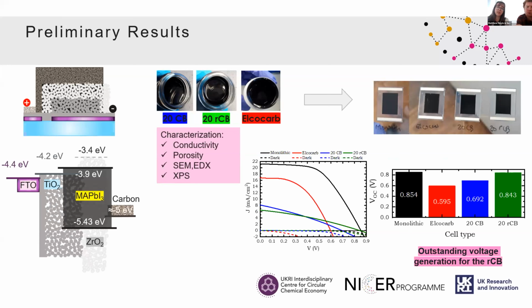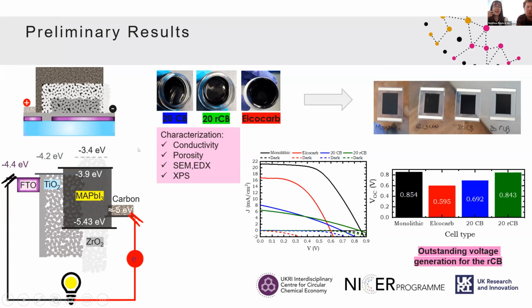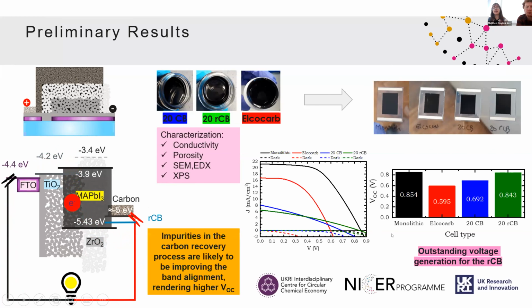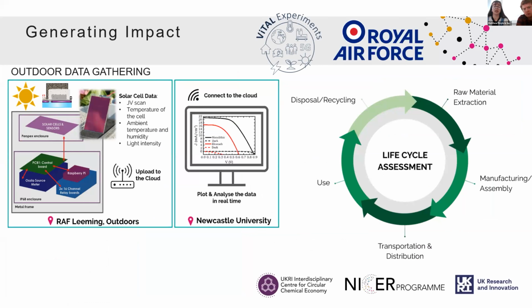But when I mentioned the charge extraction layers before, what I mean is how do they aid extraction? Basically, if you connect a circuit or any load to the solar cell and then you illuminate the perovskite, you're going to be producing electrons that jump towards the conduction band, and then they get extracted by jumping into the conduction bands of the other materials and then running back and getting re-injected through the carbon. So if we were an electron, for example, and we had to run downstairs as fast as we could, obviously we would run faster if the steps are smaller. So what we think has happened here is that the recovered carbon black has lowered this step, the valence band of the carbon, and that is what makes the open circuit voltage bigger. And this has to do mainly with impurities. Obviously, we need to keep doing more testing and optimization, but we're proving the point that yes, we can make perovskite solar cells using recovered carbon black.